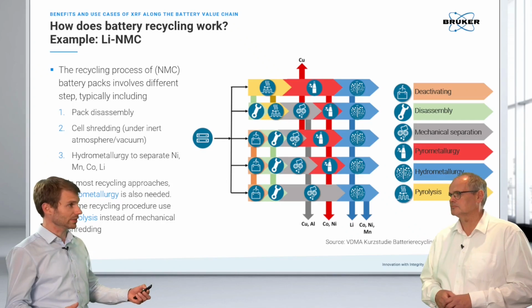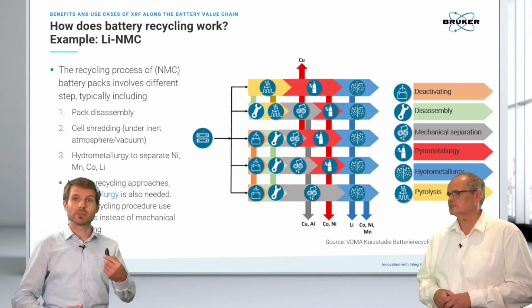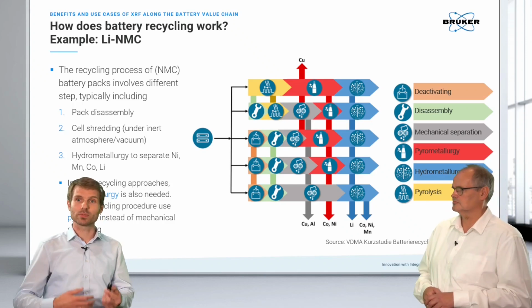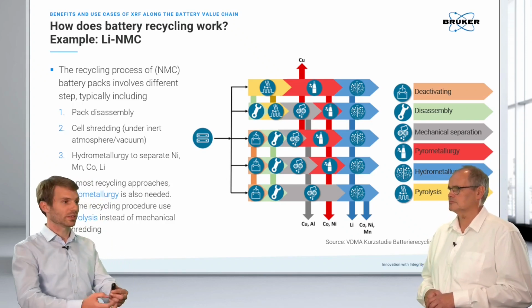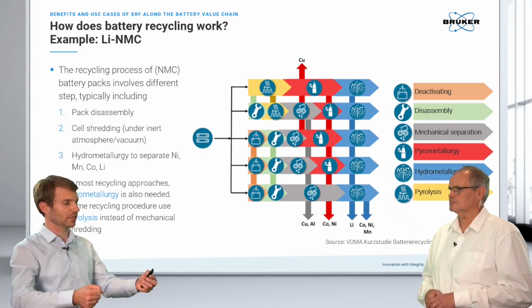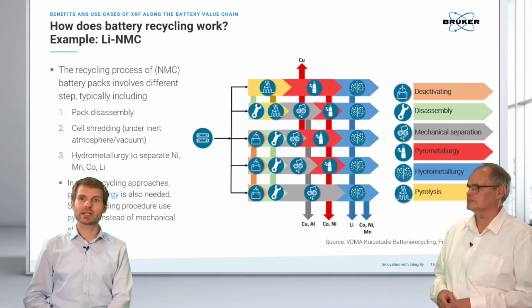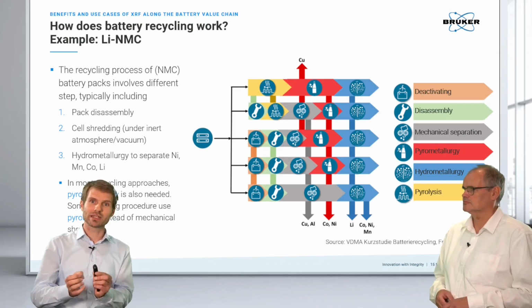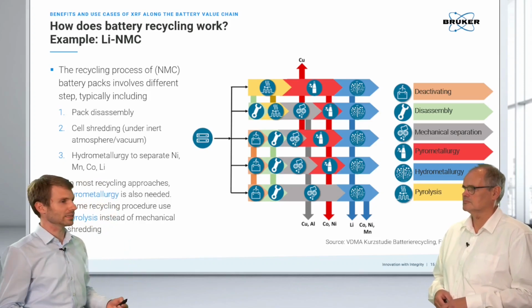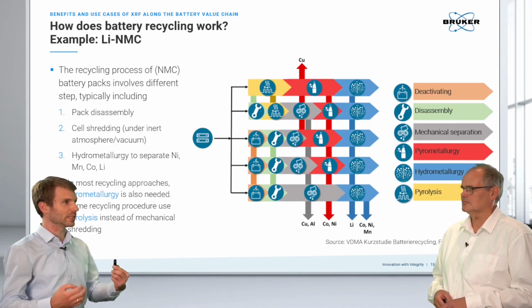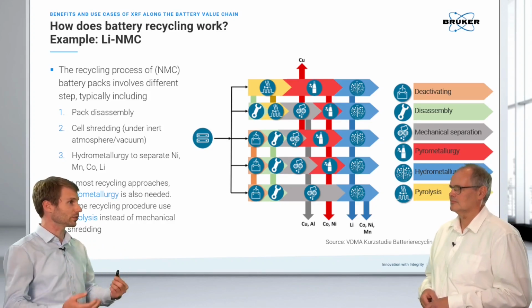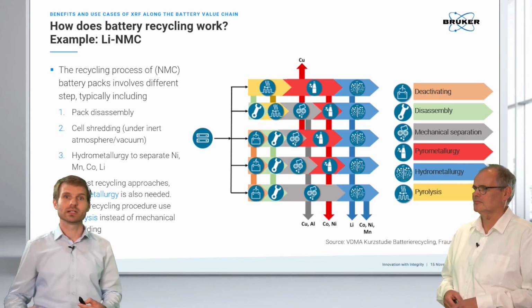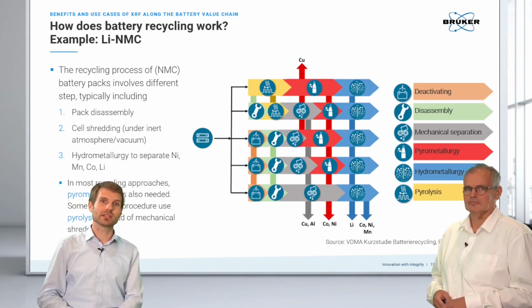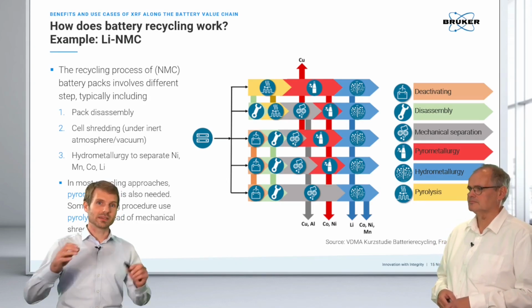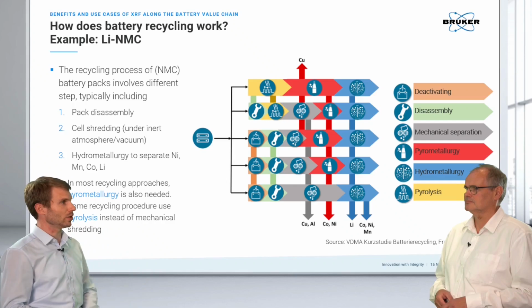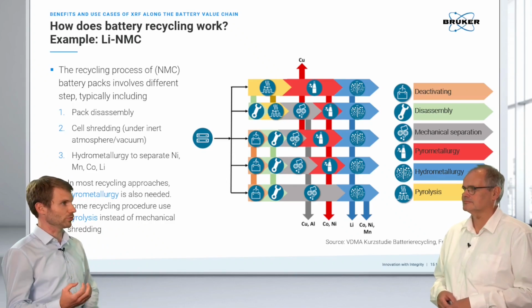Typically, these recycling processes involve some sort of mechanical disassembling, shredding, and separation process. Once you have removed, for instance, the shell of a cell and the racks, you have to shred the inside of the shell. And this is quite an energetic process. So in order to avoid combustion or hazardous moments, you need to do this in an inert atmosphere. And then you have at some point what we call the black mass of a battery,